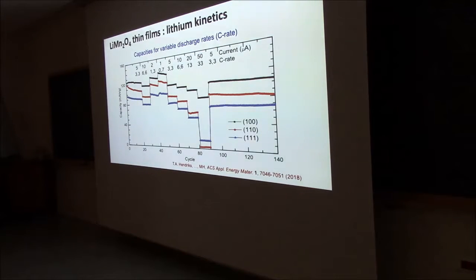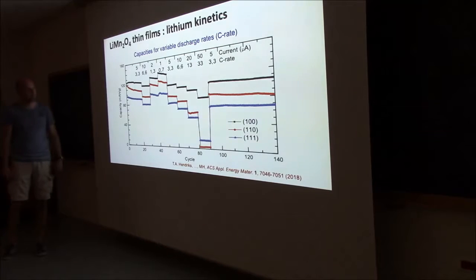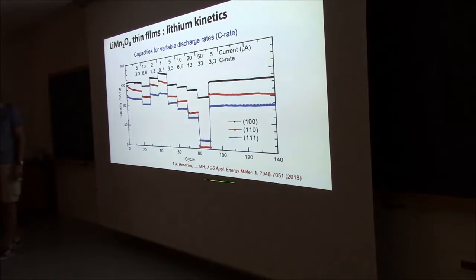And in our opinion, this has to do with the orientation, which is the internal structure of your film, because on the top, the crystal face is always 1:1, there's no difference. But with the orientation, although it's a 3D structure, there's still a preference for the 100 for lithium to move a little bit faster through the material than the other ones. And that's what you see coming back here, that when you push it to this higher range, that's when it's showing up, that it really is still able to move with a higher ionic conductivity. Now these things I'm showing you here, this was published at the end of last year, this paper, if you want to look it up.